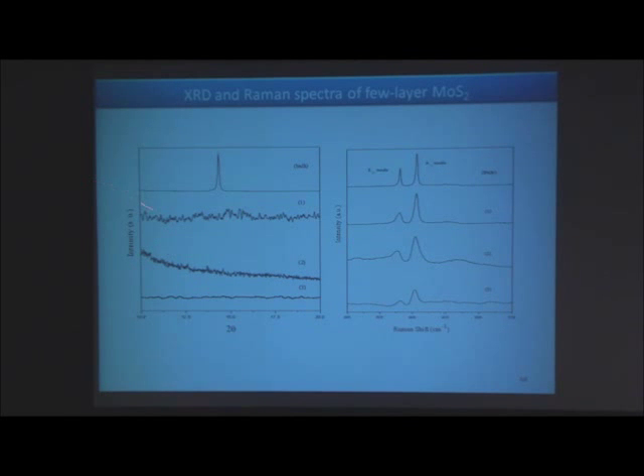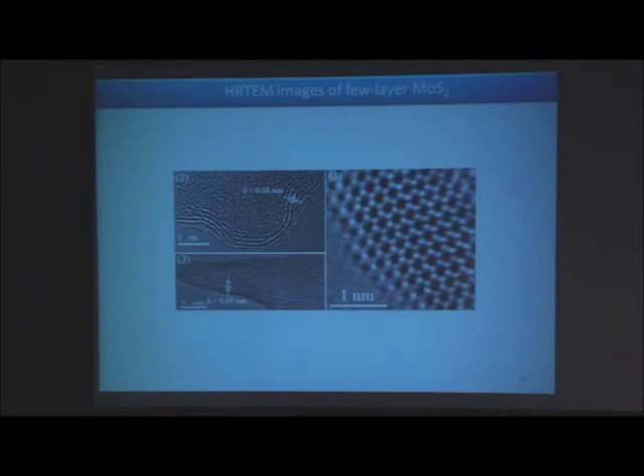And how do you know that? You see, this is the 002 reflection of MoS2. The minute I make single or 2-layer molybdenum sulfide, that reflection goes off. 002, okay? And of course, Raman spectra also changes. I will not be talking about that. It takes time. And you can see this is a 2 or 1-layer molybdenum sulfide with every atom shown there.